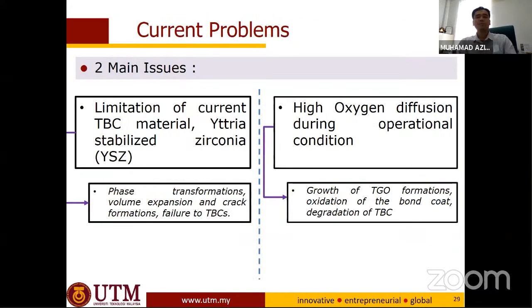So two issues here. First is the limitation of the current TBC material, YSZ, where we see the transformation, volume expansion, and failure of the TBC. Another issue is the high oxygen diffusion during operational conditions. So there is growth of TGO formation, oxidation of the bond coat, and degradation of the TBC. This is basically the issue.